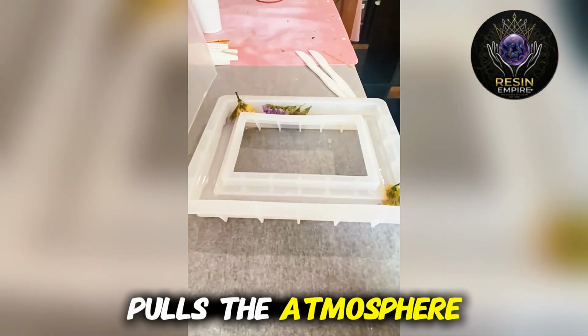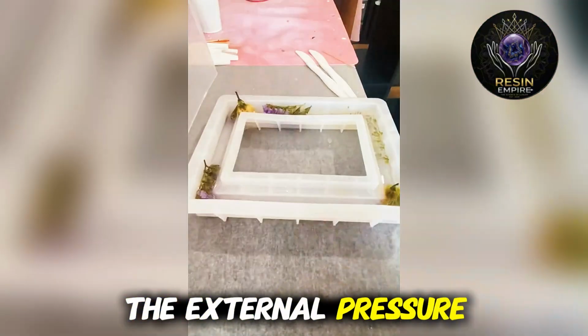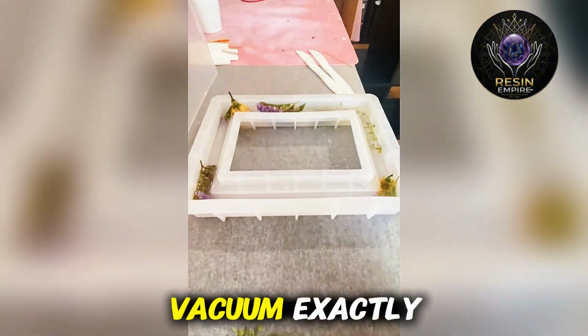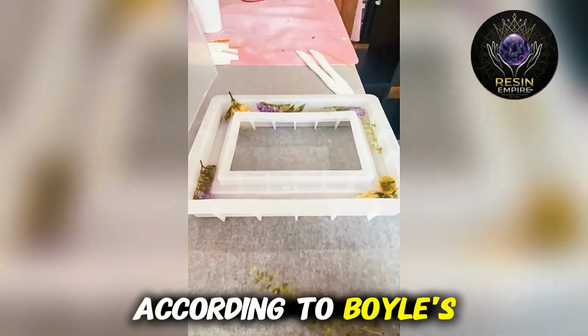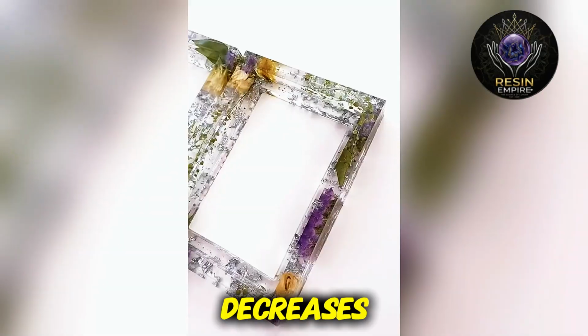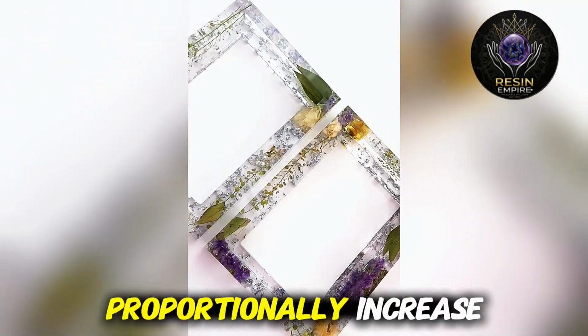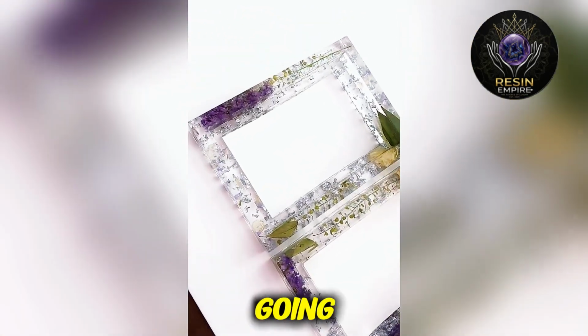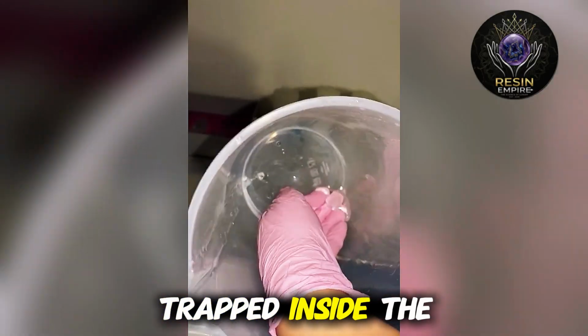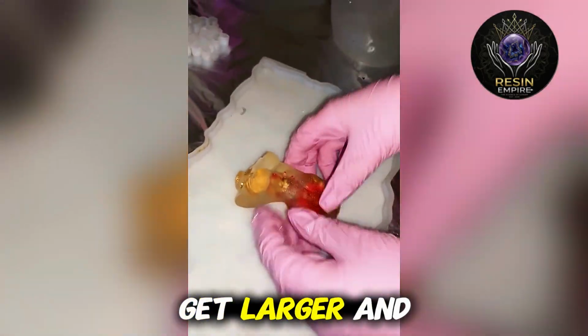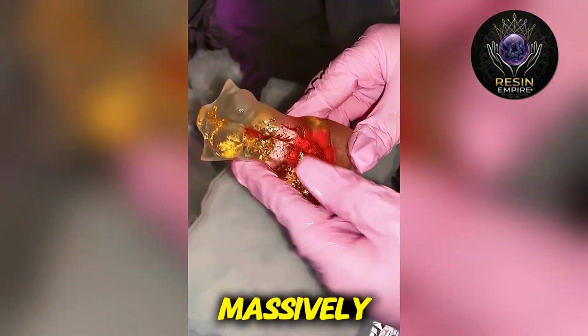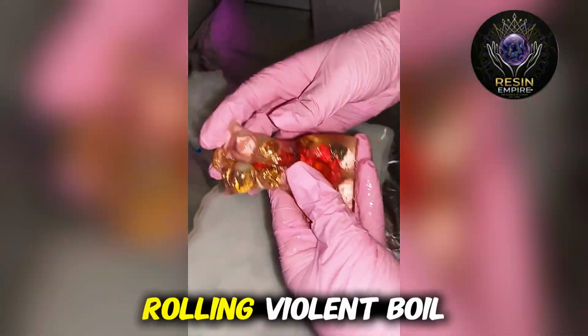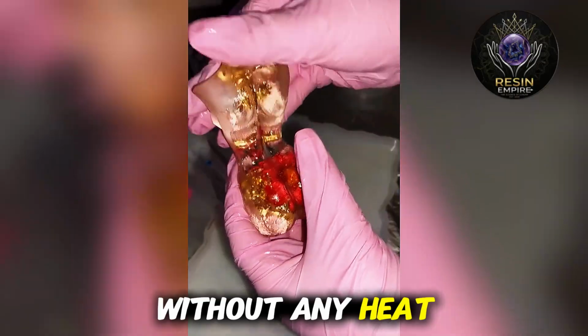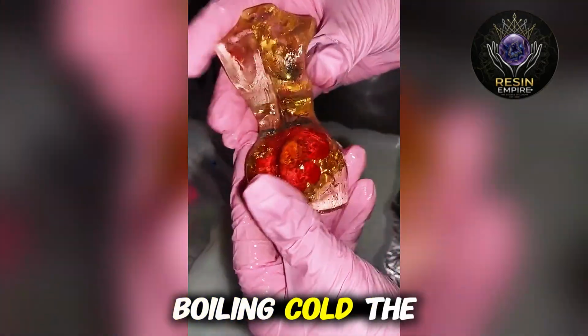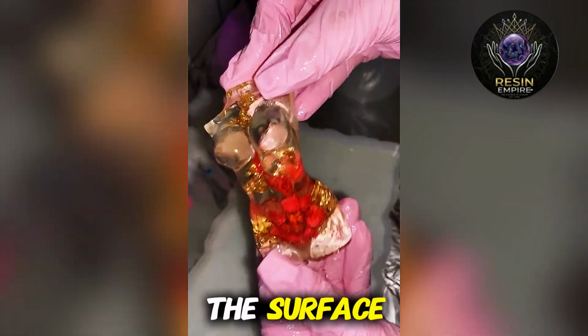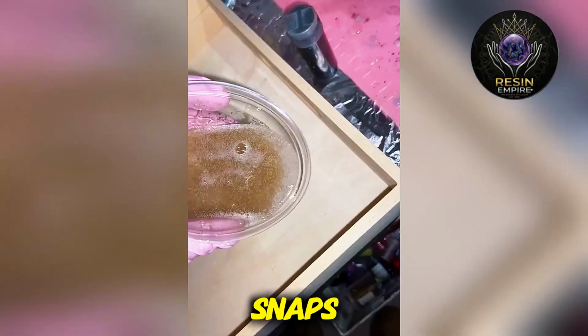As the pump pulls the atmosphere out of the chamber, the external pressure on the liquid plummets. It's creating a vacuum. Exactly. According to Boyle's law, as the pressure around a gas decreases, the volume of that gas must proportionally increase. Ah, I see where this is going. So the microscopic air bubbles trapped inside the liquid resin rapidly expand. They get larger and larger, their buoyancy increases massively, and the resin essentially begins to look like a rolling, violent boil without any heat. Wow, like it's boiling cold. Boiling cold. The bubbles rush to the surface, stretching the polymer skin until it snaps.